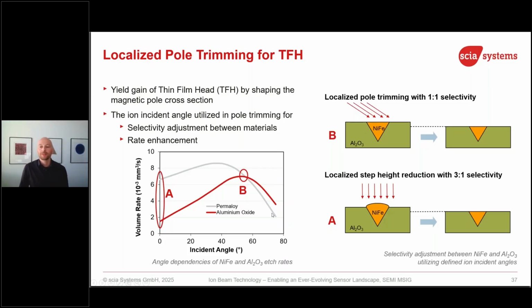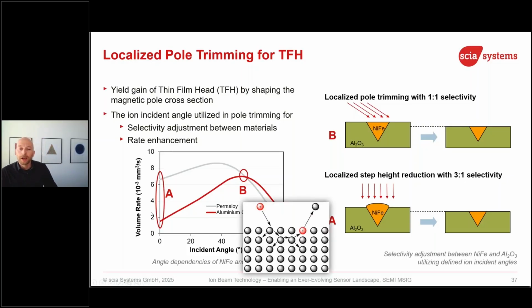One could use it also the opposite way. Maybe you have from your CMP some dishing and something like that. And if this is measured with an AFM, we could correct it also. All pre-calculated, as this kind of step is different over the wafer. On each position, you have a different step height. Then ion beam trimming could be used to correct the step height over the wafer. Just a reminder, again, why do we see this kind of change here in sputter rate or sputter yield? It's a normal physical effect. So imagine an ion is coming here under a certain angle. If the angle is smaller, at some point it's easier to release the atom. But if the angle is too small, then the ion would be reflected. So just a little bit of physical background again. Why do we have those behaviors here?